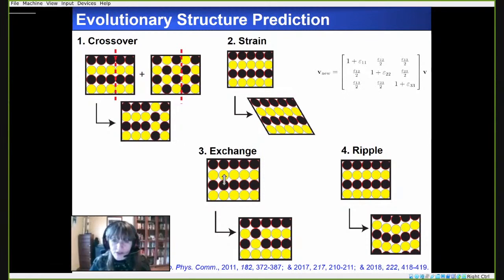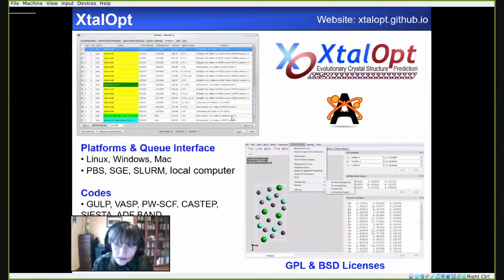Then these go out to be optimized to the nearest local minimum. And then you just repeat this process until hopefully you have converged to find the most stable global minimum for the desired stoichiometry that you're looking at, and then compute its properties. So we've developed an algorithm to do this. It's called XtalOpt. XtalOpt is cross-platform. It can also work with a variety of local queuing systems and codes, including those based on density functional theory and interatomic potentials. And it's available under open source licenses such as GPL and BSD. It also comes with a nice graphical user interface, and it is interfaced with Avogadro, which is a very nice way to analyze, create, and visualize chemical systems.